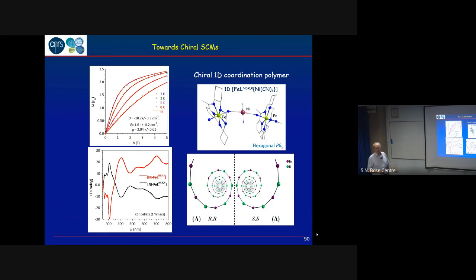In one plot, you were showing chi was increasing with decreasing magnetic field. How do you explain that? Because when you reach the saturation, you get the susceptibility from delta M versus the field you are using. But this is correct only if you are in a domain where you have a linear growth of the magnetization with the field. But if you reach a system with a large magnetic moment, it's very easy to be out of this regime because you saturate the system. This is why we measure at lower fields. So chi is in emu per Tesla.